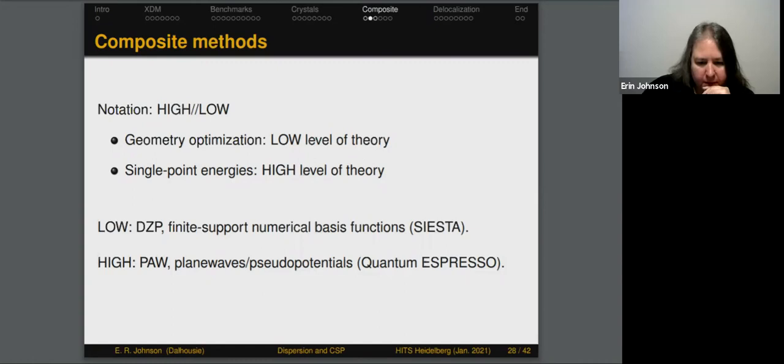The notation for these is usually written as high/low. So we have the energy method followed by the geometry method. Our proposal for a composite method is to perform geometry optimizations with a small basis set, a double zeta plus polarization basis set using finite support numerical orbitals and the SIESTA code. And then our high level method is the plane wave pseudopotential Quantum ESPRESSO code. The results I've shown so far for crystals have been carried out with Quantum ESPRESSO and the projector